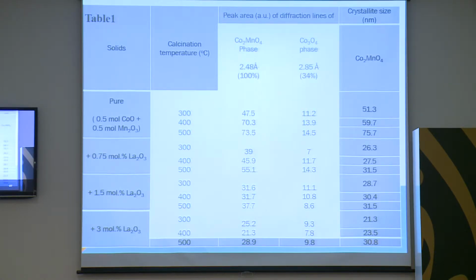Also, the crystallite size for different solids was calculated by using the Scherrer equation. And the crystallite size of the main phase Co2MnO4, as in this table, refers to the doping process with lanthanum oxide in the range between 0.75 to 3 mole percent leading to decreasing the crystal size as a whole.